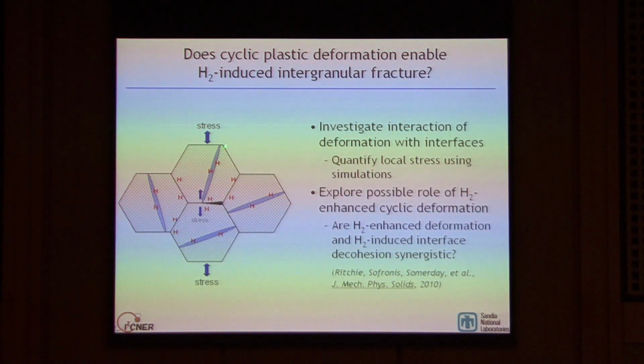If we apply a force or displacement to these metals, that can only be accommodated for so much by elastic stretching of atomic bonds. Eventually, to accommodate more displacement, we have to generate and propagate crystal defects. Often, the nucleation and propagation of these defects happens in very discrete bands. If these bands of plastic deformation intersect with grain boundaries, they can form stresses locally. So we can get elevated local stresses acting in concert with the remote stress to enable fracture, enabling cracking along these grain boundaries, especially in the presence of hydrogen.